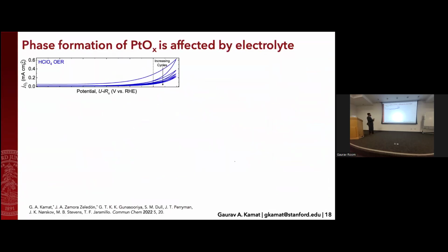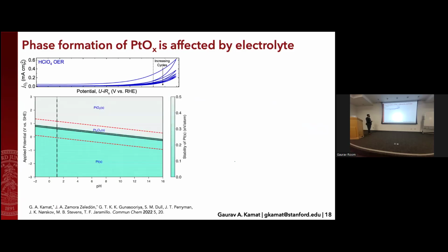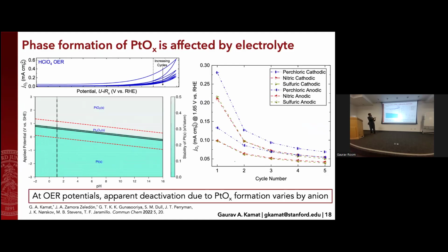Another thing we saw in this study, particularly for the oxygen evolution reaction, is as we cycle this platinum electrode up and down in potential, you actually start seeing the performance degrade a little bit over time. If we look at why that may be, this is a potential versus pH diagram that shows what phases are expected to be thermodynamically stable at various conditions. As you go from this platinum solid phase and apply a higher and higher potential, you see that platinum oxides are starting to form on the surface. And if we look at how exactly that rate of catalyst deactivation changes as these cycles go on, the apparent deactivation varies by anion. So what ion you have present appears to also change how fast your platinum may oxidize and therefore deactivate your active platinum surface.